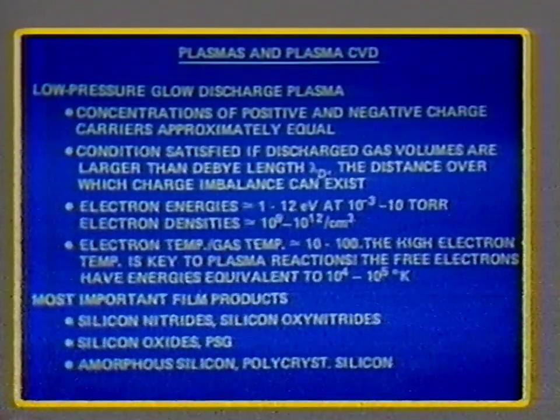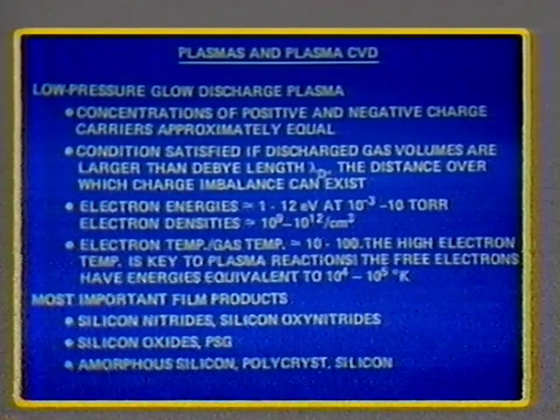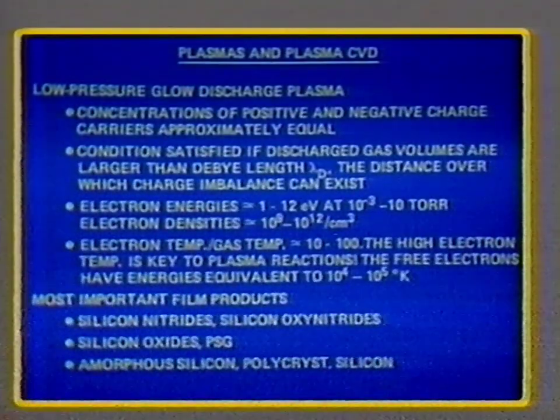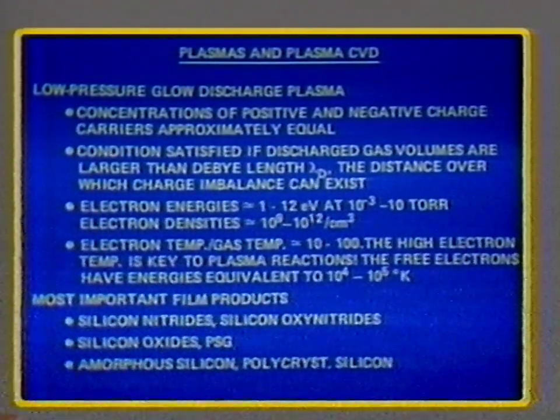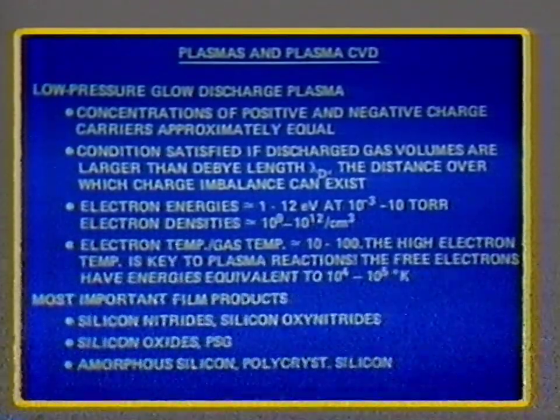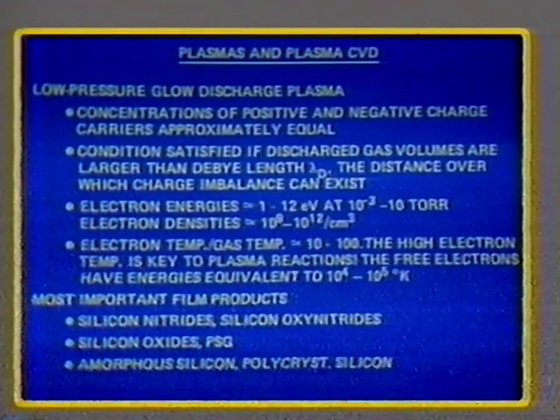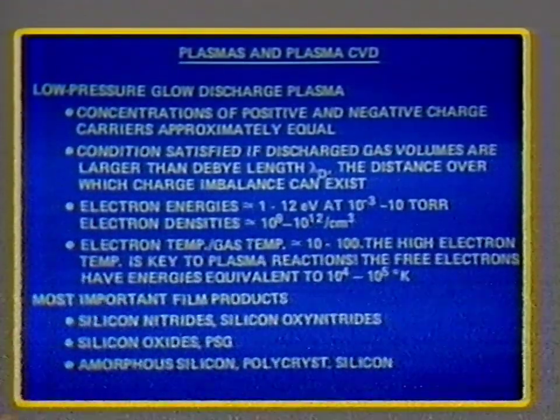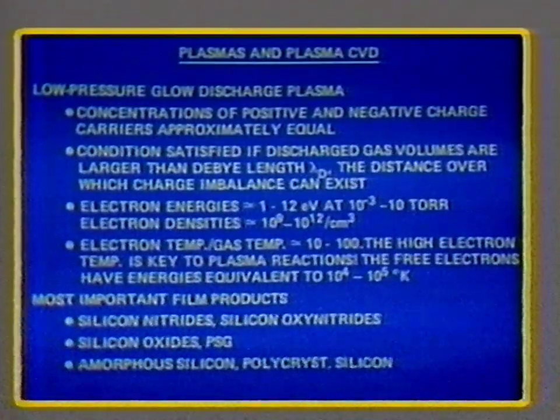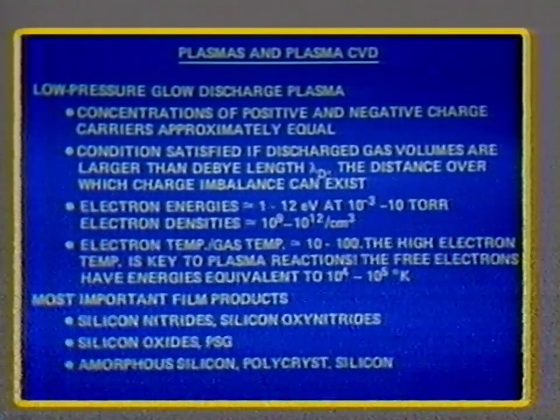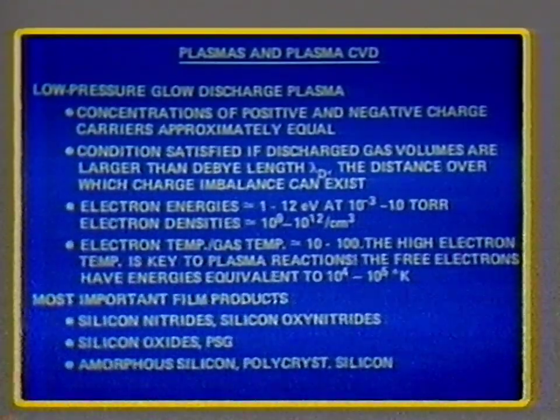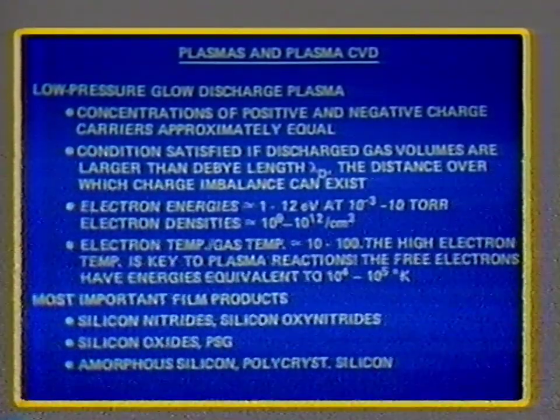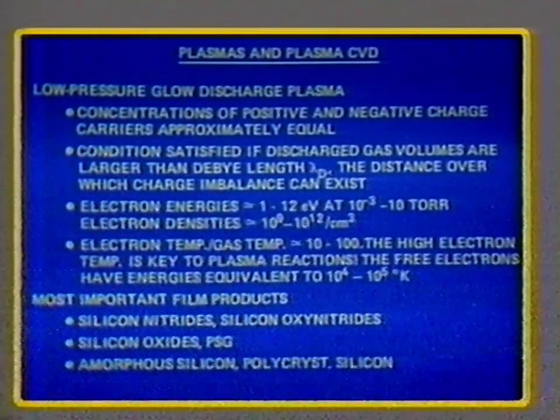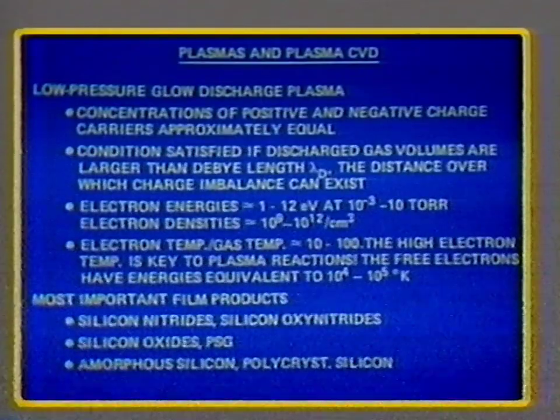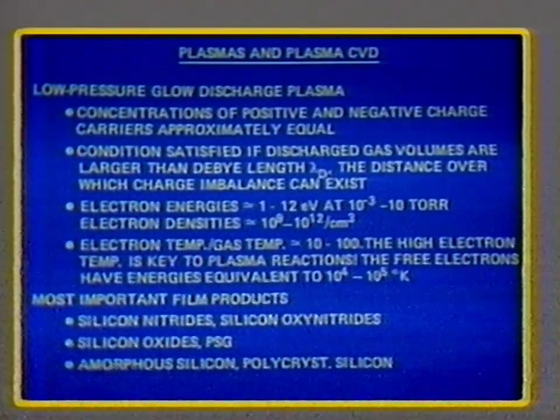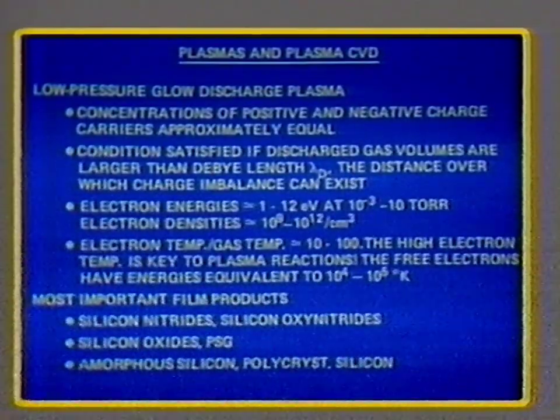As far as the low pressure glow discharges are concerned, and those are the ones, of course, we are really using, I have indicated here a number of points which are important in creating the glow discharges. Essentially, perhaps the most important aspect is shown down here. The electron energies are in a range of 1 to 12 electron volts in the pressure range of 10 to the minus 3 to 10 torr, and electron densities in the range of 10 to the 9th to 10 to the 12th per cubic centimeter. Now, the electron temperature over gas temperature ratio is in the range of 10 to 100.